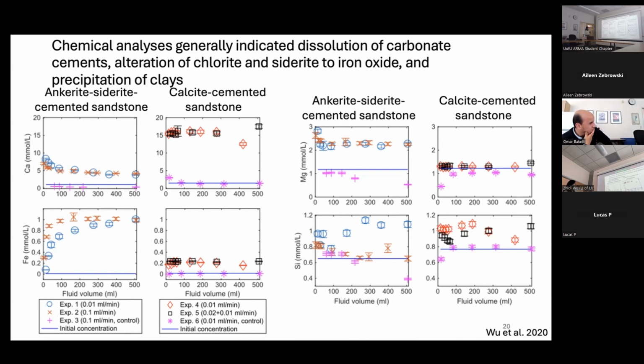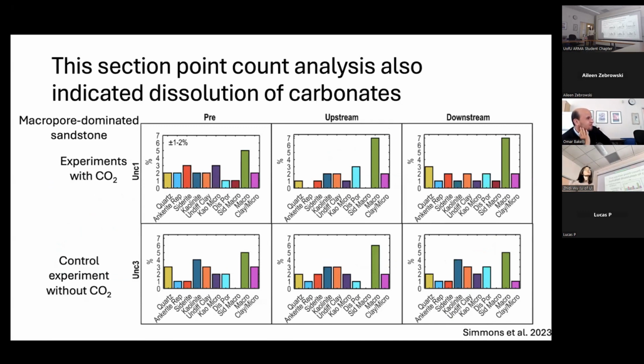The iron concentrations increase and then they stabilize. So there are also siderite and chlorite dissolution happening as well. As for precipitation, I think we will see more evidence of that in the XRCT images. So this provided evidence that dissolution actually happened in the rocks, and it is mainly carbonates. Same with the thin section data. These data also reinforce our evidence that there is dissolution of carbonates.